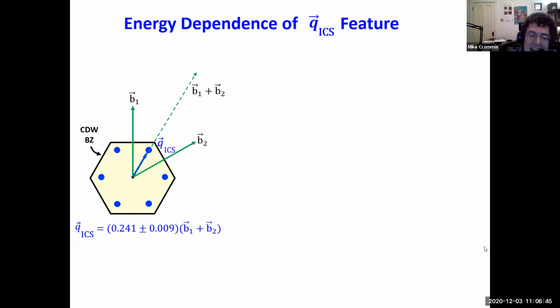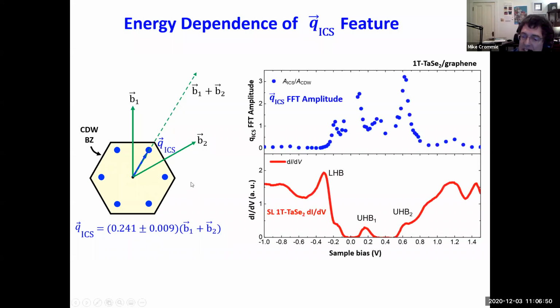And so let's take a look at the energy dependence of this new ICS feature. Here's the Fourier transform amplitude of this peak as a function of energy, and we can see that it has its highest amplitude near the Hubbard band edges. So in the Hubbard band region, this Fourier transform amplitude is really high, but as we move to lower and higher energy, it falls off dramatically. So it's really localized mainly in this Hubbard band region. It has a strong energy dependence.